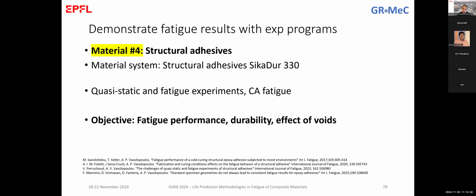What we did here, we did a lot of studies. If I want to talk about this material I can talk for hours, because we investigated structural adhesives for more than 10 years, and we have a lot of results on quasi-static and fatigue experiments. And usually we try to investigate the fatigue performance, but also the durability, so the effect of the environmental conditions for these materials, because these materials are used in engineering applications in the open air, so you have the effect of the environment. And we also try to investigate the effect of voids, but actually it's the effect of the material itself